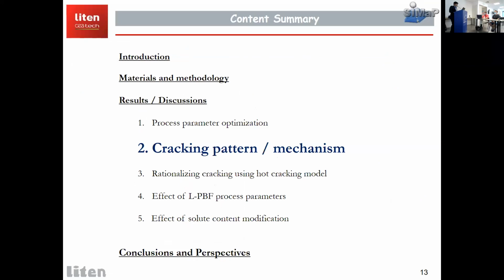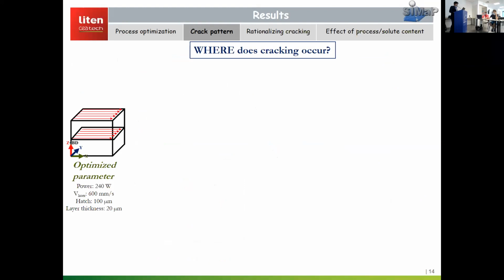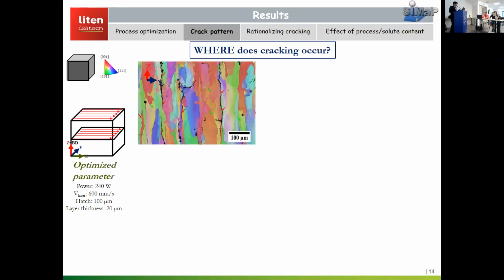So moving into the cracking pattern, what is the cracking pattern and what is its mechanism? To first identify where the cracking occurs based on the microstructure, we chose the sample which was optimized, which was least in cracking, and we analyzed its EBSD microstructure along the building direction. And we clearly see that cracks are present in the microstructure along the building direction. And those are specifically along the grain boundaries.